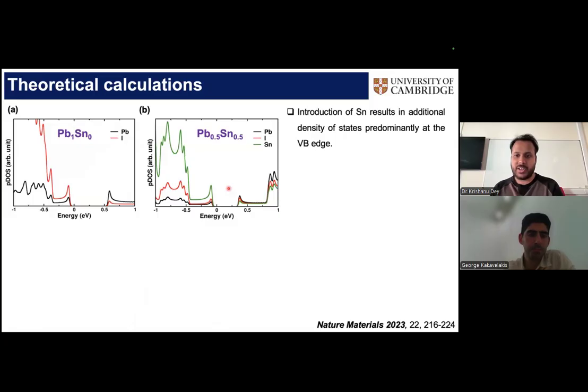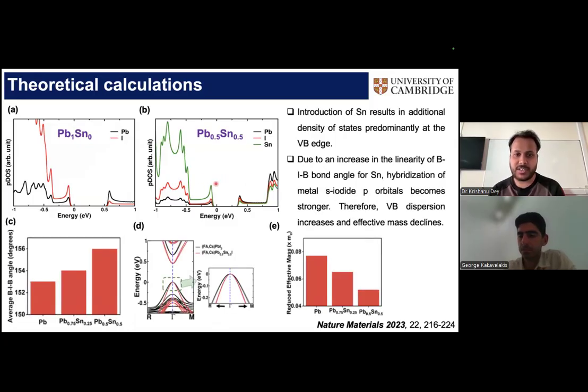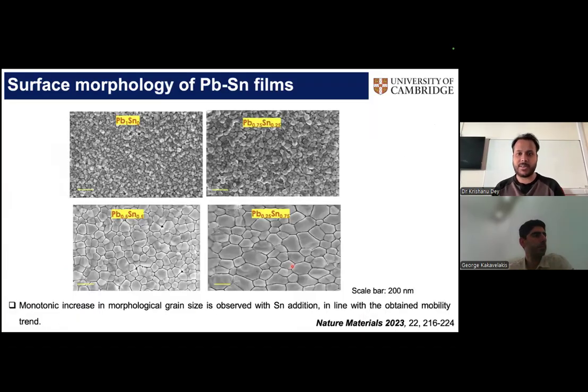Anyway, we did some theory calculations with some of our collaborators, and we found that including some tin adds some additional density of states in the valence band maximum, which can explain why you are getting predominant p-type transport in the presence of tin. And when you do band structure calculations, you find that the curvature of your valence band maximum increases with tin, and we know that the curvature is related to the effective mass. So the stronger the curvature, the lower the effective mass, and this is the decreasing trend we see as you introduce more and more tin. Then we looked at the surface morphology using SEM, and we also find that increasing the tin increases the average grain size of our films, and this is in agreement with the obtained mobility trend.